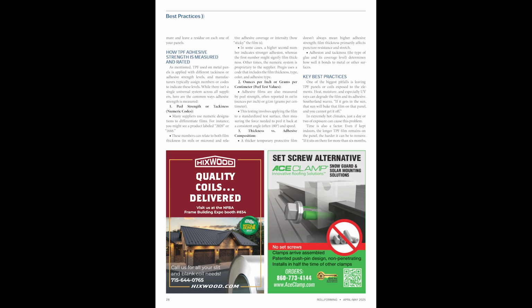Key best practices. One of the biggest pitfalls is leaving TPF panels or coils exposed to the elements. Heat, moisture, and especially UV rays can degrade the film and its adhesive. Sutherland warns, "If it gets in the sun, that sun will bake that film on that panel, and you cannot get it off." In extremely hot climates, just a day or two of exposure can cause this problem. Time is also a factor. Even if kept indoors, the longer TPF film remains on the panel, the harder it can be to remove.